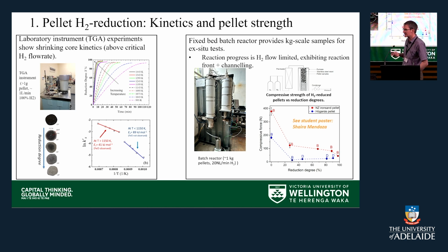So this is some data that Sara, one of my PhD students, was showing in the poster session. You may already have seen it if you talked to her. But we've been able to look at generating large numbers of pellets and doing ex situ strength tests. And one of the things we find about this particular material is that because we've got all this titanium that we exsolve as we reduce the pellets, we form this very brittle ceramic structure inside the pellets, which means that our pellets undergo brittle failure even when they're fully metallized, which is not ideal if you were looking at something that you want to briquette at a later point.